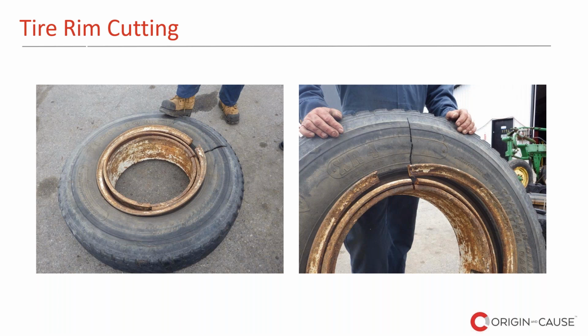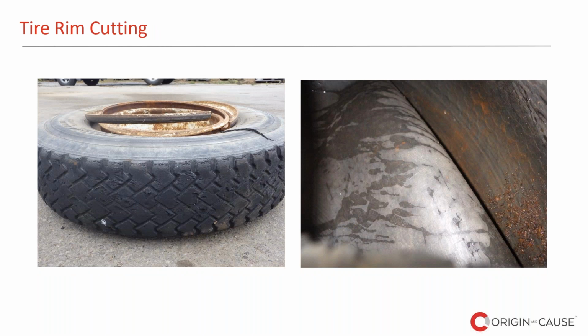However, during cutting, the saw he was using cut back, causing him face injuries. He suspected that the owner of those tires put some explosives inside the tires. So that was his allegation. However, our investigation revealed the fact that he was negligent in cutting those tires, and when he cut through soft material, he used a certain speed, but when he reached the actual rim itself, because it was harder, the saw cut back, hurting him. There was no evidence inside of any explosives.